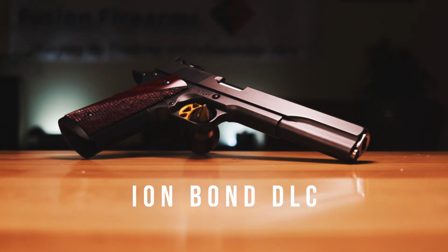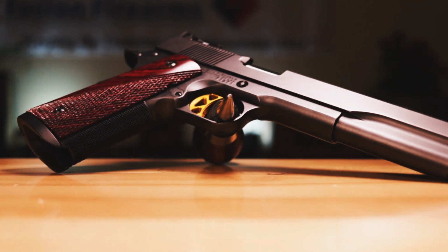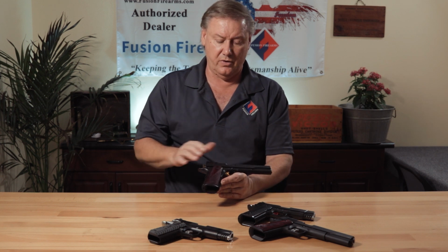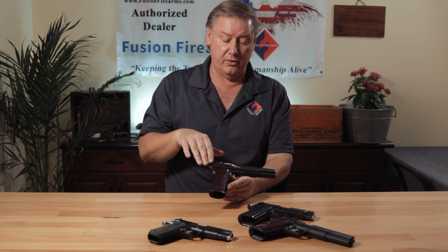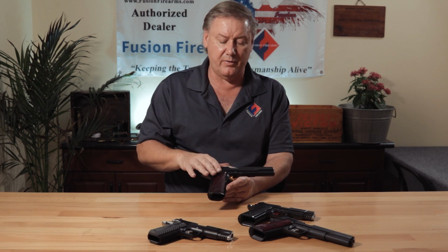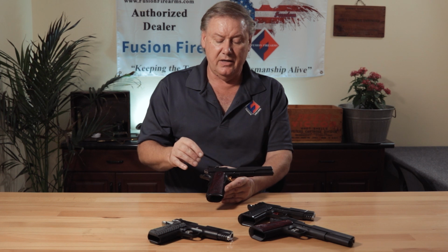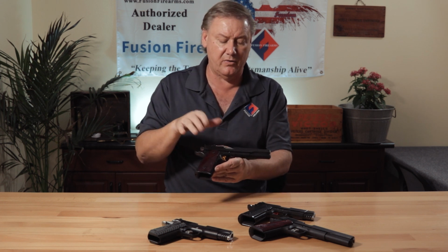The next coating I'll move into is the Ion Bond DLC. Ion Bond DLC is diamond-like coating, and it is very thin. A lot of it has to do with how the parts are prepped prior to coating, and also the actual coater that's doing the work for you. Some of the most problematic finishes I've worked with in my life have been Ion Bond DLC, for inconsistencies. It has to be done in a vacuum chamber. The vacuum chamber has to be extremely clean. The gun parts, everything, no oil, no water, no moisture. You get one little droplet of moisture floating around in the vacuum chamber, and boom, you've got spots and inconsistencies in your finish.